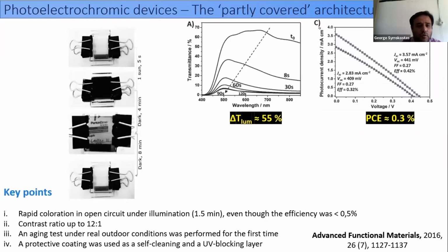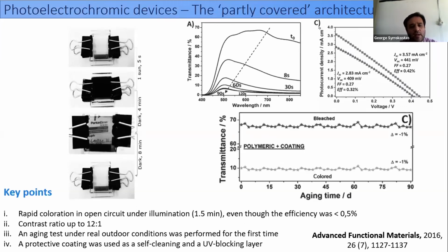The most important point in this work was that here we can see photos of this device in different operation states, and we proved that such a device can be stable even after exposing it to real outdoor conditions. Here we see the transmittance values in the initial bleached state and in the colored state. We see that the values are very constant even after 90 days of exposure to outdoor conditions. That was an aging test performed for the first time then, and I believe the only time until now, since the stability of these devices is usually examined using continuous cycling.